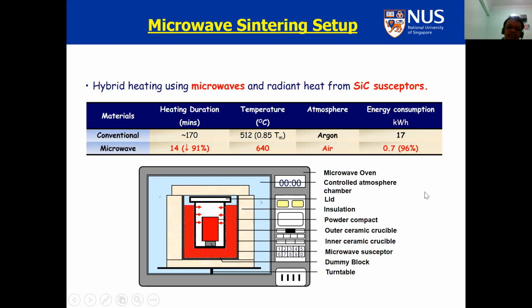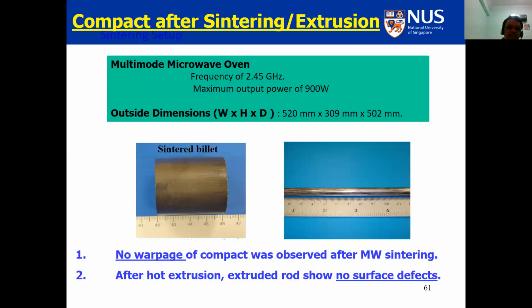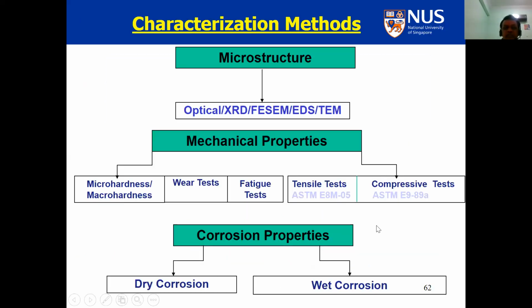Efforts are being made to take this to the industrial level now. You can get the billet, you can extrude that, no defects, nothing. And the cost of this setup is only like $2,000. Very cheap. So once you have made a material, you claim your material is good, you claim your processing is good, but it is no good unless it also shows good properties.